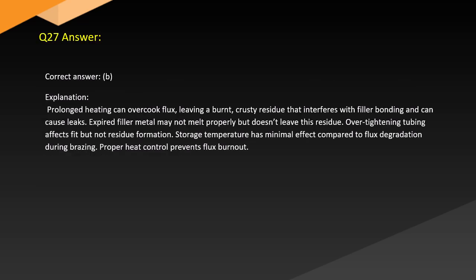Answer. Correct answer: B. Explanation. Prolonged heating can overcook flux, leaving a burnt, crusty residue that interferes with filler bonding and can cause leaks. Expired filler metal may not melt properly but doesn't leave this residue. Over-tightening tubing affects fit but not residue formation. Storage temperature has minimal effect compared to flux degradation during brazing. Proper heat control prevents flux burnout.